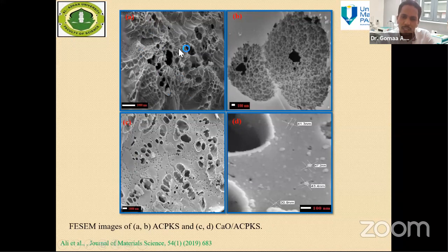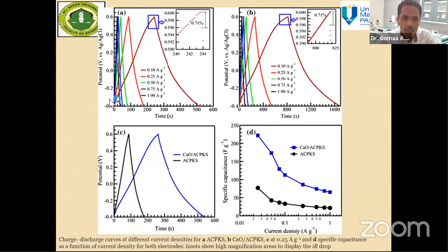And this porous carbon structure is interesting for the electrochemical application or supercapacitor application, since it allows the ions to accumulate or penetrate among this porous structure. And here is some of the electrochemical testing of these composites or nanocomposites, showing charge discharge time with very low, here we call it IR drop in the supercapacitor application. So this material shows very low IR drop, around less than 0.7%. This IR drop indicates whether the material is conducting or resistive.